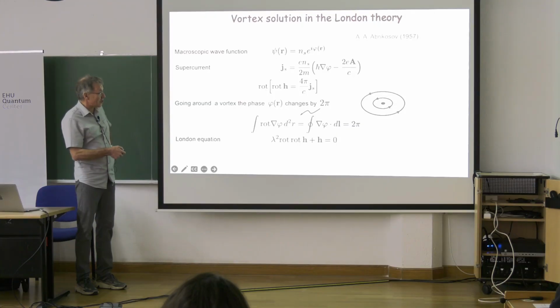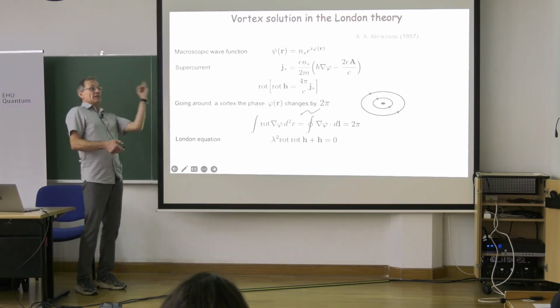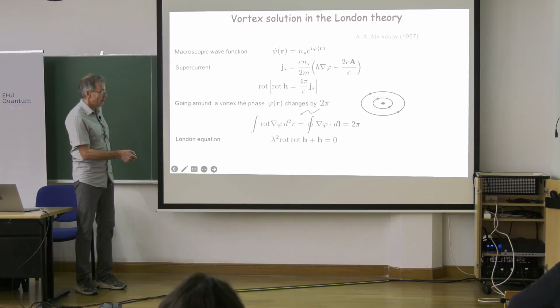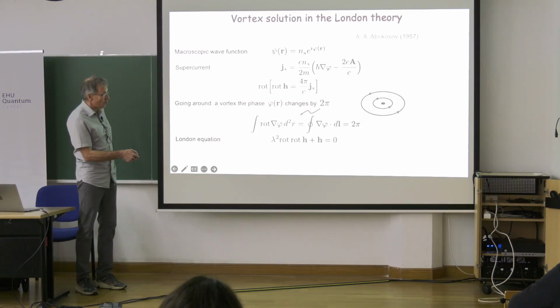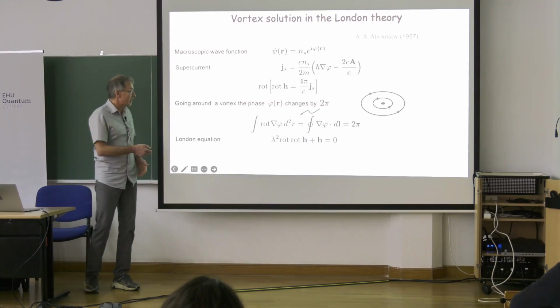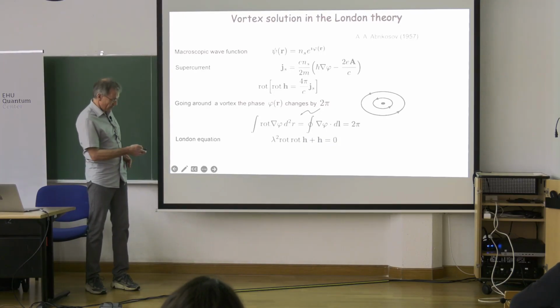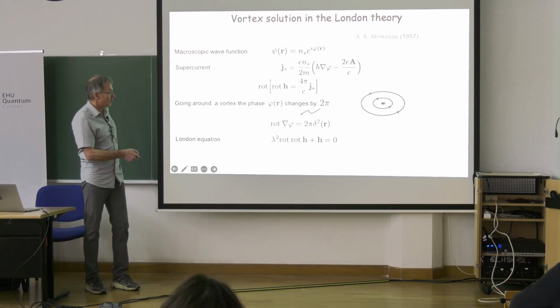Because if we integrate the rotation of the gradient, from Stokes' law we transform the area integration to a contour integration, and now we integrate gradient phi over the contour, which would be phi here minus phi there, and if it changed by 2 pi, you get 2 pi. So the integral would be 0 everywhere where this point is not included in the contour, and it would be constant where we integrate around this. Which means that this thing is actually a delta function. Rotation of gradient is a delta function.